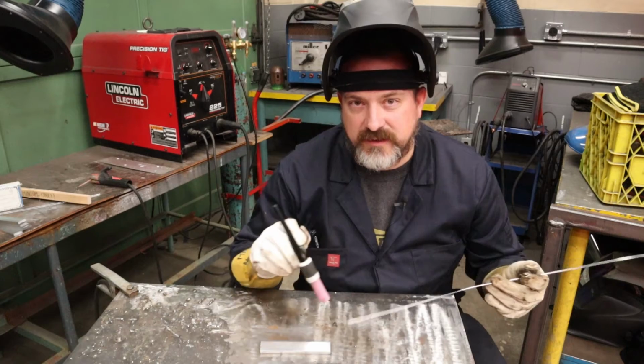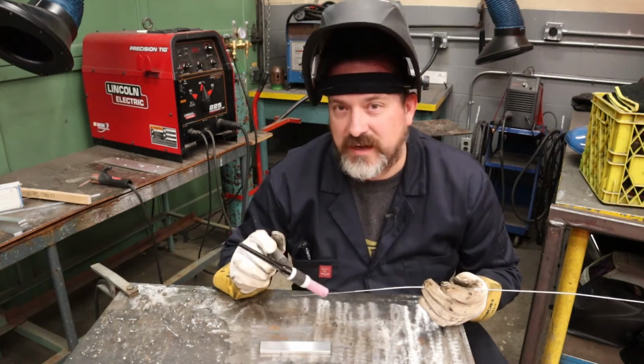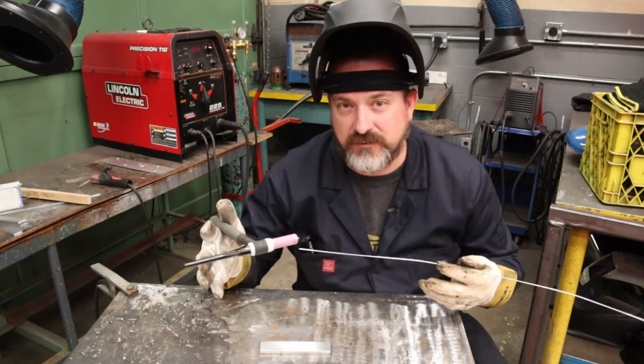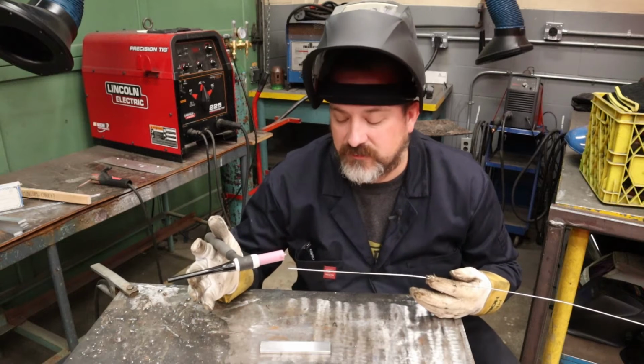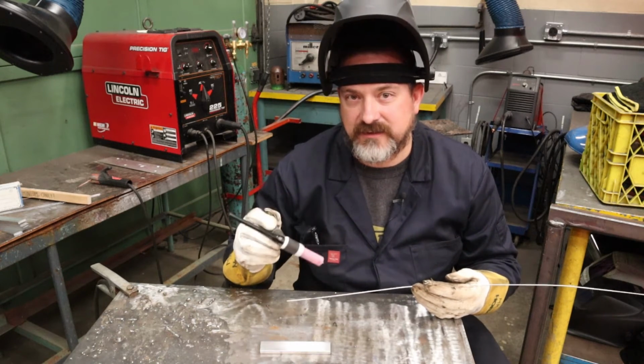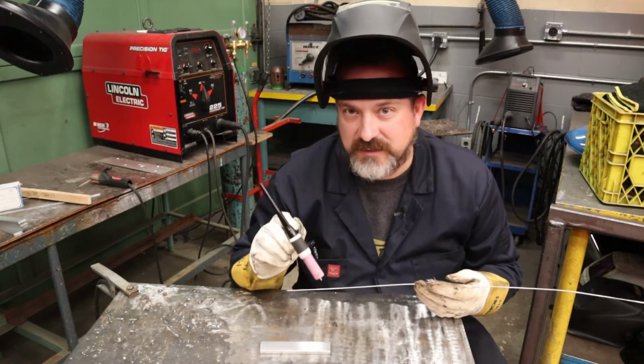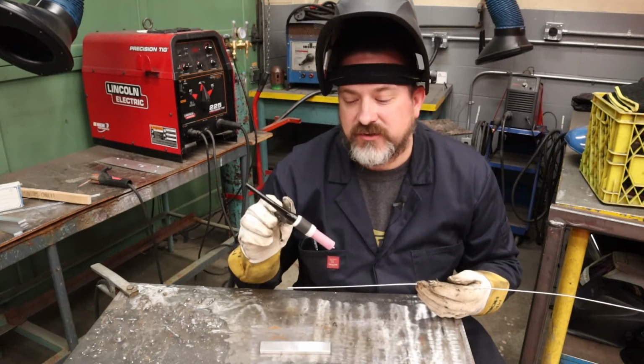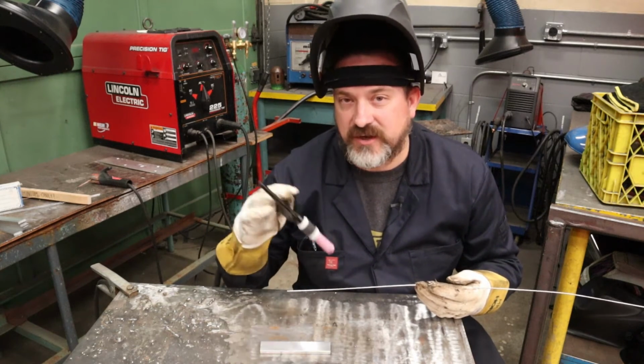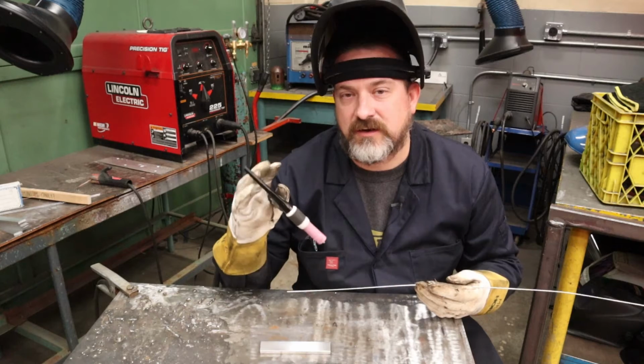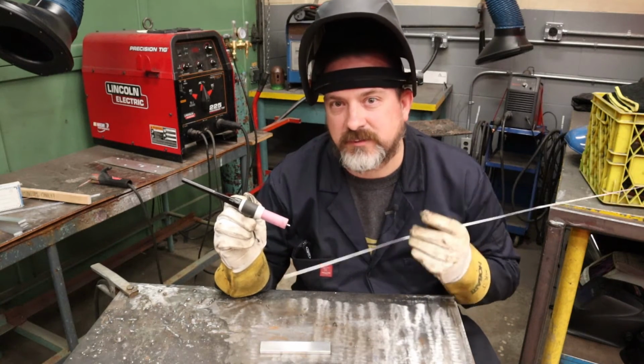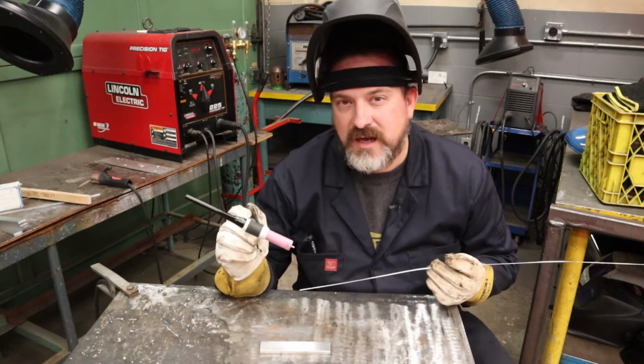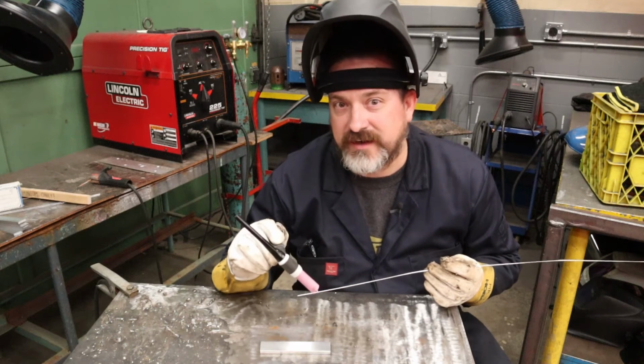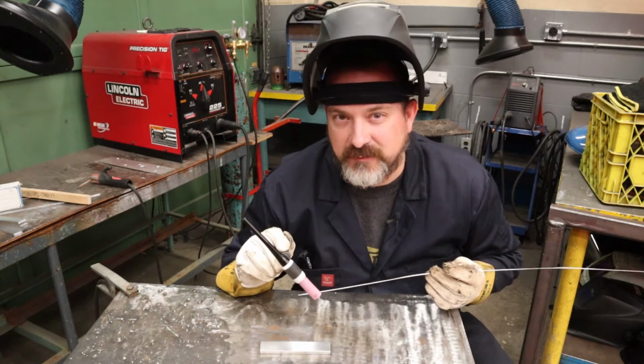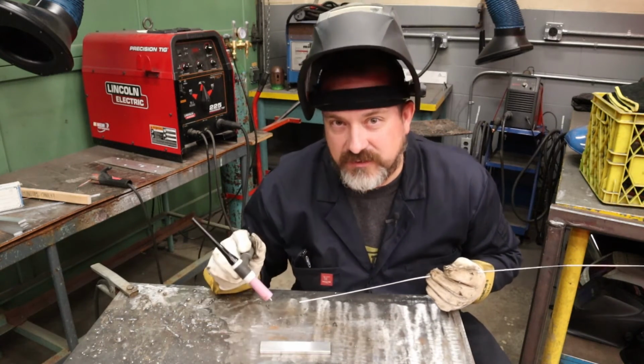Now, as you're welding, when you get to the end of the piece, you have to back off because there's less material for that heat to dissipate and it will get hot for you. The other thing is when you are just about done and ready to pull away, don't just let go of the pedal. You're going to have to slowly back it off as you're still slowly adding a little bit of material from the filler rod. Otherwise, you will end up with a hole or a crater. And when we're doing aluminum, it could be susceptible to having some cracking start there.